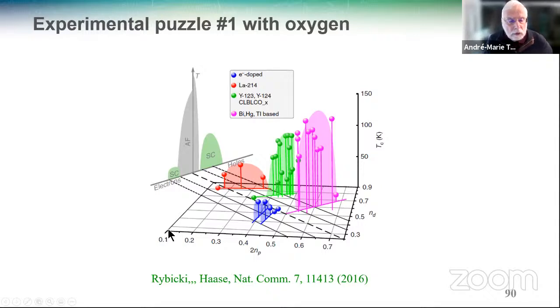Okay, and now there are two axes because there are two types of atoms. There's the oxygen, that's called oxygen hole content, 2NP, and this is the copper hole content that I call ND. Okay, so now look at that filling here. I can be at half filling if I have 5 electrons now in my unit cell. Because there are 3 atoms, so I can put 6 electrons. If I have 5, I'm at half filling as far as the Hubbard model is concerned. Now along this line here, I get ND plus 2NP is equal to 6. So 5, I'm sorry. That's the half-filled case. Okay, and then I look at some other doping. So there are several values of ND and NP that give the same doping. And the point of this plot is that you see that for a given doping here, I have different families of superconductors, right? And they have different TC.